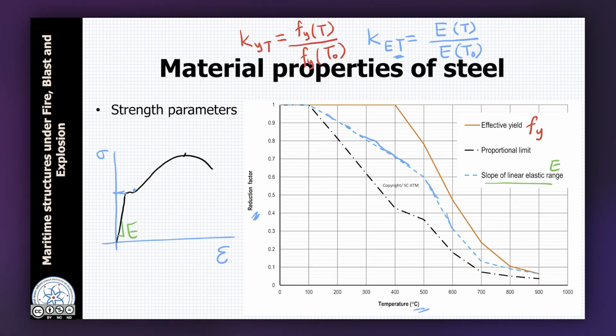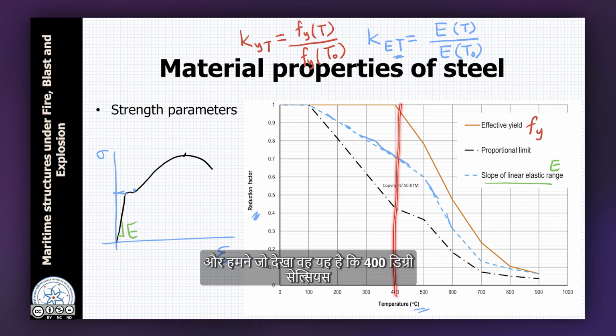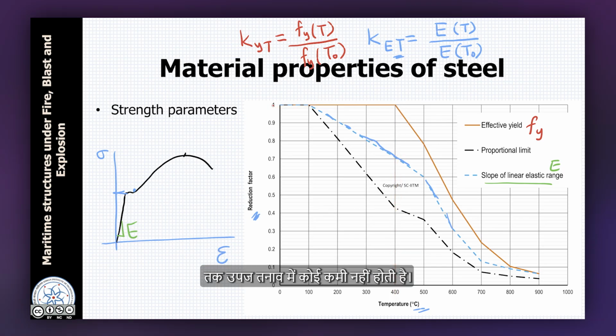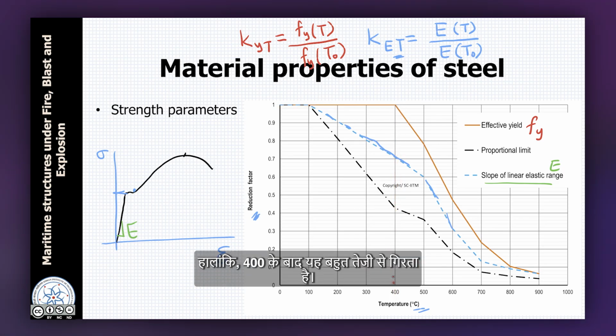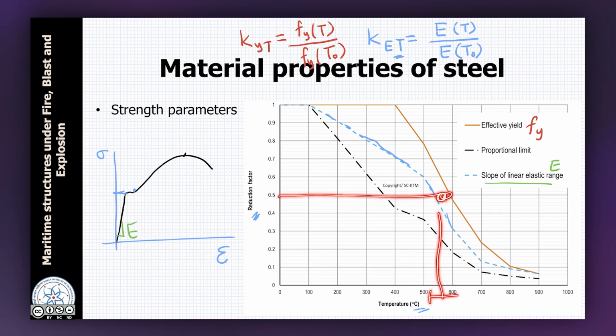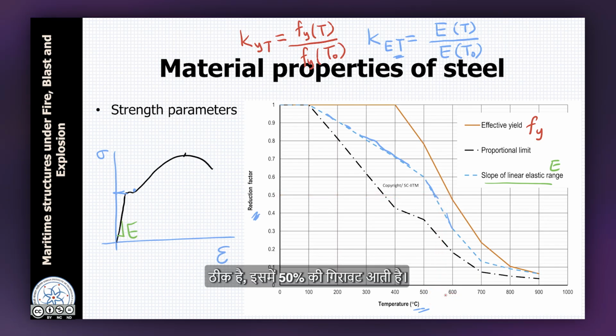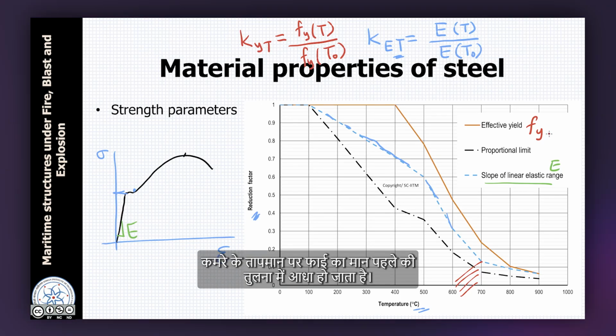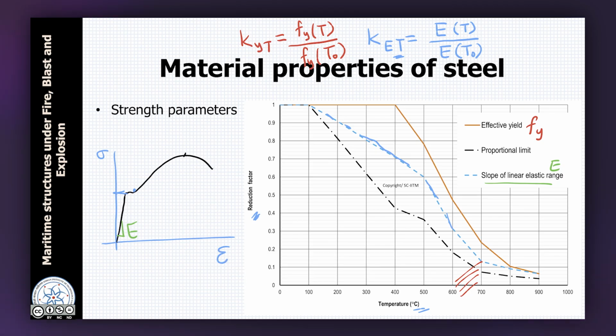degrees Celsius. And what we notice is that up to 400 degrees Celsius, there is no reduction in the yield stress. However, after 400 it drops very rapidly, so much so that again between the 500 and 600 range, it drops by 50%. So this is the range where steel loses half of its strength. Fy becomes half of what it used to be at room temperature. So these are the strength parameters.